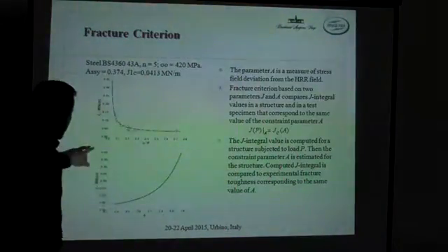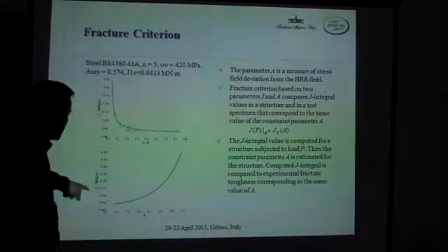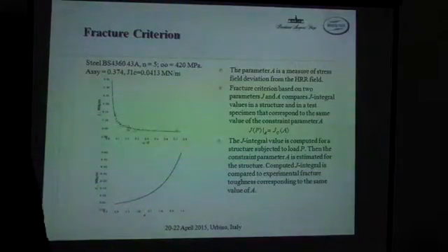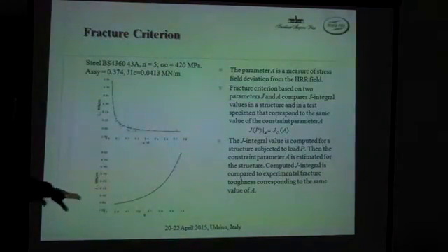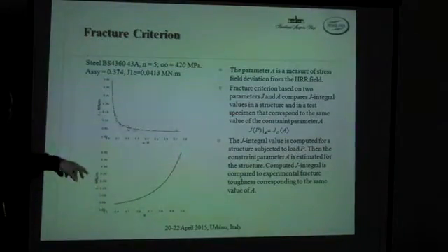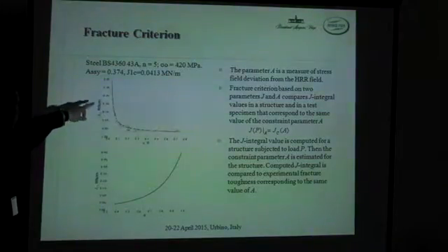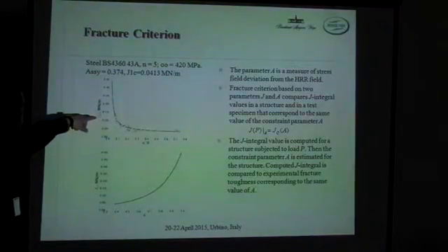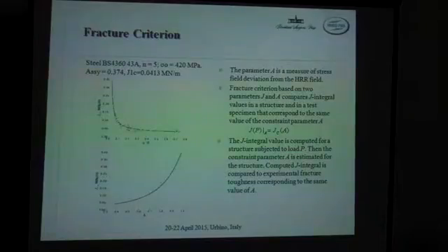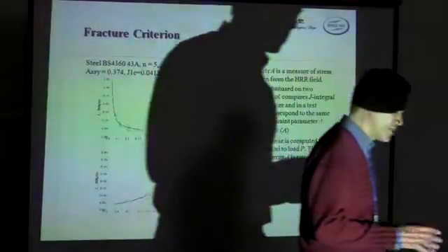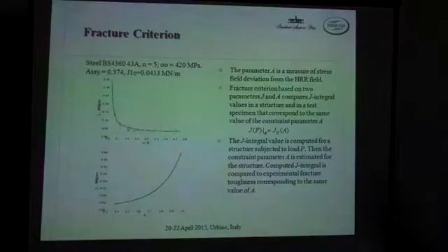So the dependence of the elastic-plastic fracture toughness on the A parameter as a constraint parameter would be considered as a basic curve or master curve. And I would like to say that this curve was obtained by recalculated experimental data from this picture, J_C against the crack aspect ratio, which was obtained for the same configuration of specimen under bending, but thickness was changing.